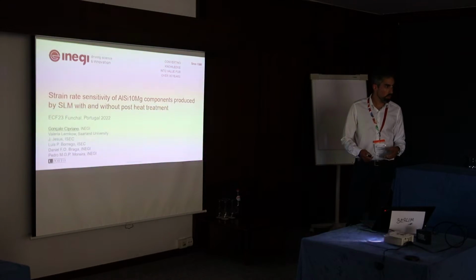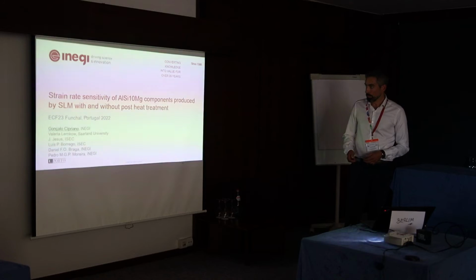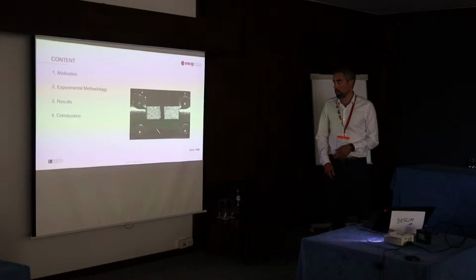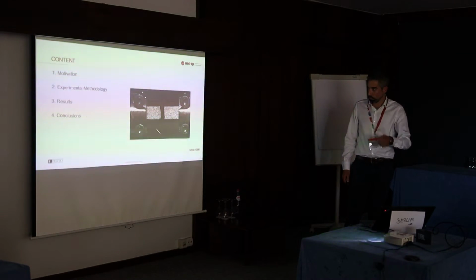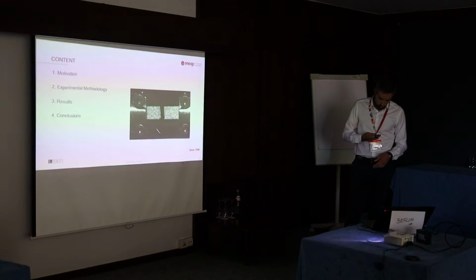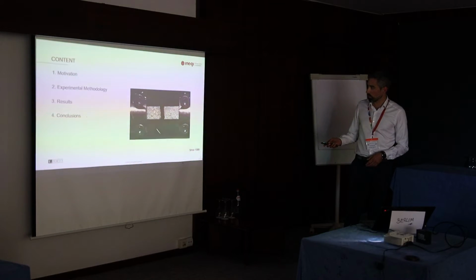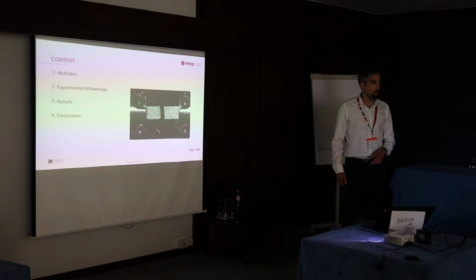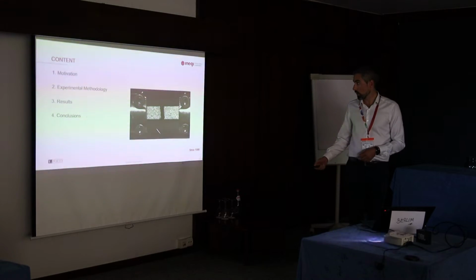As the title says, this was an investigation regarding laser powder bed fusion producing components, and we wanted to understand the influence of the direction of printing on the strength of these components, the effect post-heat treatment would have, and how these materials would respond to high strain rate deformation. So I'll go over the motivation for my work, the experimental methodology that we carried out, the results and some conclusions. And here on the side you have an example of one specimen that was produced and tested in a split Hopkinson bar apparatus at a strain rate of 300 per second.